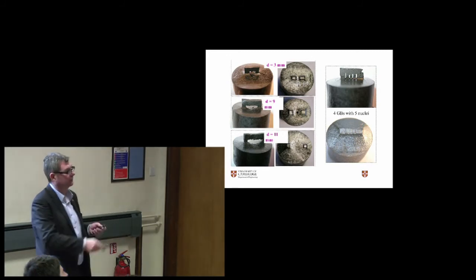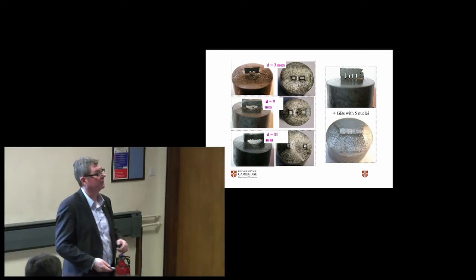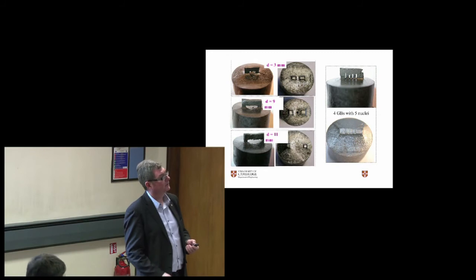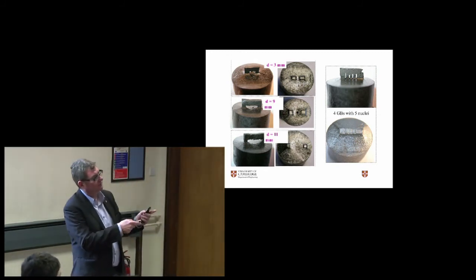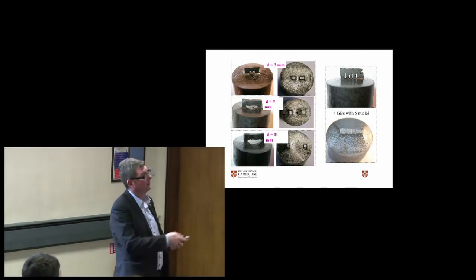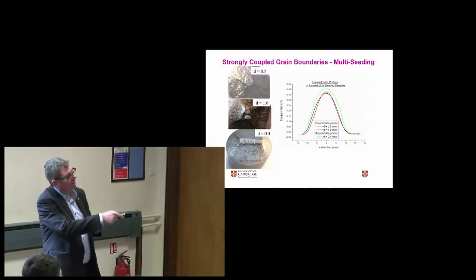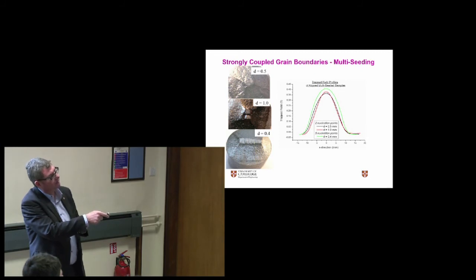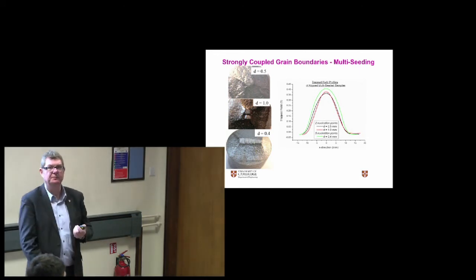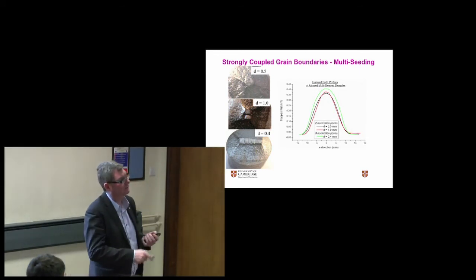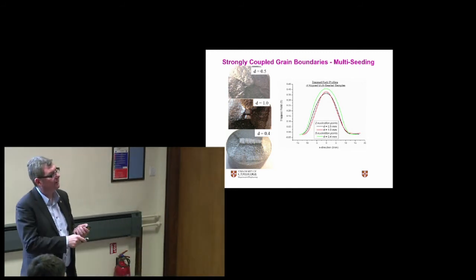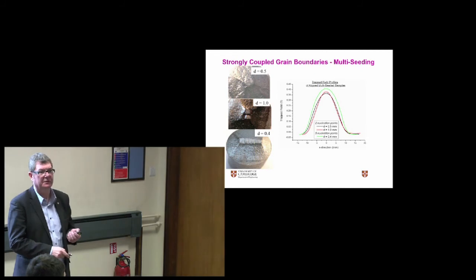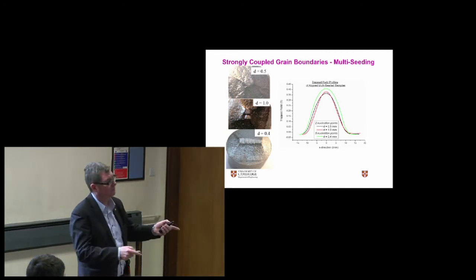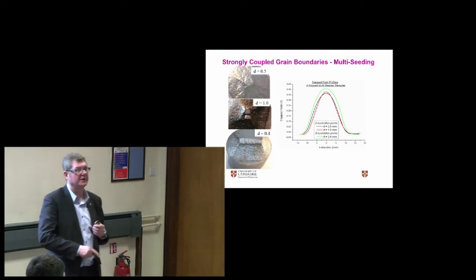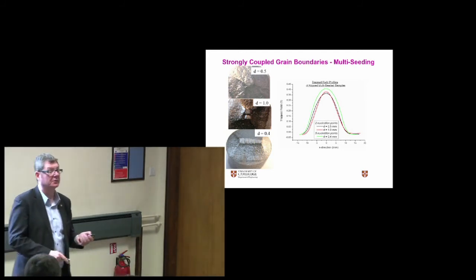So the question is, what are the properties of these grain boundaries? Because we know that in rare earth barium cuprate, the grain boundaries are not very kind. And common wisdom was that it was the separation that critically determined whether the grain boundary was any good. So if you measure trapped fields of these different materials with small separations, bigger separations, and a large number of seeds, you get roughly the same profile. That tells you the length scale of the current flow is the same, so these grain boundaries don't interrupt the flow of current. Therefore, it's not the separation that's important, it's the orientation. And if you get the orientation right, then multi-seeding should be very possible.